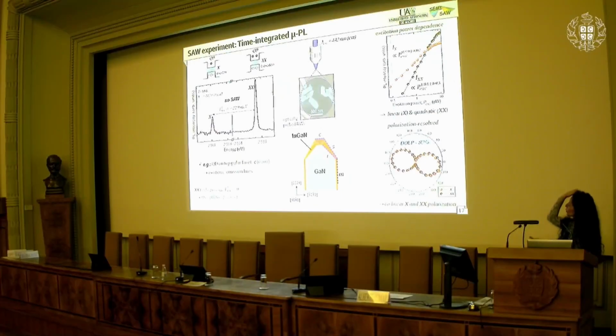So now I would like to show the effect of the acoustic wave on these nanowire quantum dots. For that, I will focus only on the polar quantum dots in this topmost nanowire region. And here you see again a low temperature PL spectrum, which shows, in the absence of the acoustic wave, such sharp lines. They correspond to the excitonic complexes, which originate from one of these probed nanowire quantum dots.